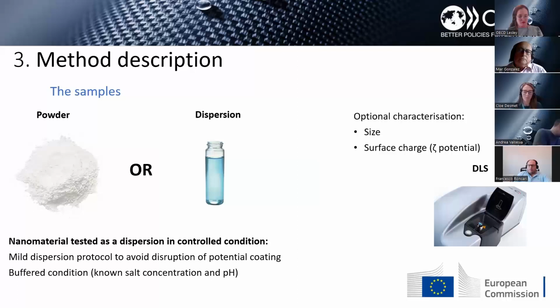The nanomaterial sample can be in two different forms, powder or dispersion. What is really important is that to disperse the nanomaterial, you use a protocol that is very mild, to avoid disruption of any potential coating. It's also important to use a buffer to disperse the sample, so a salt with known concentration and known pH value. Optionally, you can also perform some physicochemical characterization of your materials in terms of size and zeta potential through dynamic light scattering.